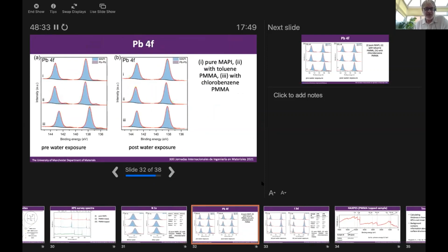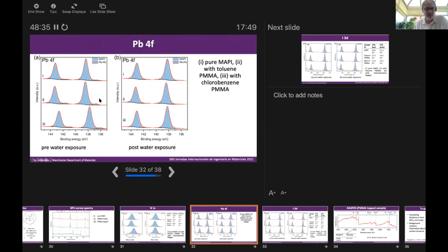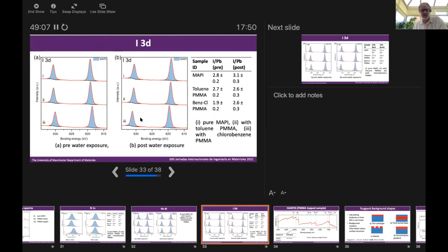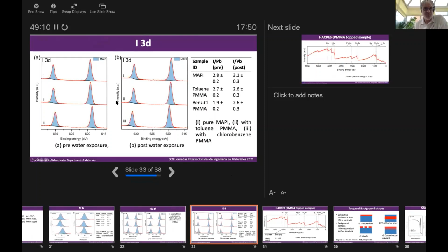The lead 4Fs again seem to support this. So this is the pure material, and then we add in polymethyl methacrylate mixed with toluene and polymethyl methacrylate with chlorobenzene. And again, we don't really see any significant differences between these. And after water exposure, there isn't a large change. The water exposure here, I should point out, was much shorter than the one in the previous example. This was less than 24 hours. So one of the things we want to do is to try to increase that water exposure time to see if that makes a difference. And again, the iodine 3D doesn't change appreciably with the water exposure.